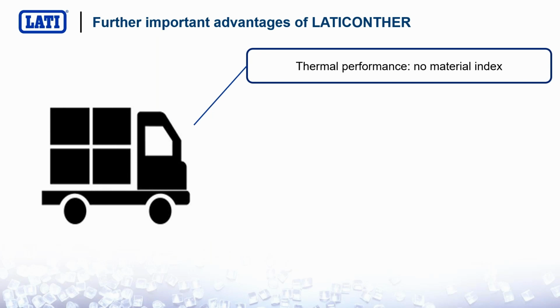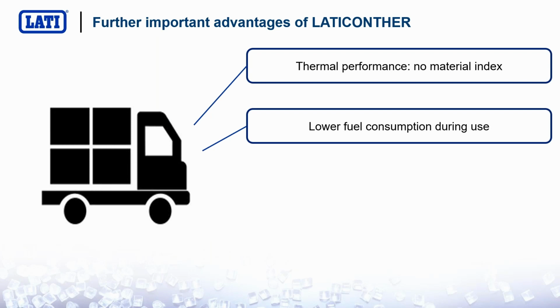For thermal performance, you will not need to change the volume of your part to have a properly working thermal management application. The geometry can be the same. Actually, it can be lighter than metals, because you have to change something to use maybe graphite orientation. So you will not be required to add volume to have proper performance. Your car featuring plastic parts, of course, will consume a much lower amount of fuel, and this will have a very big impact on the global warming potential of the full process, which also includes many transports.